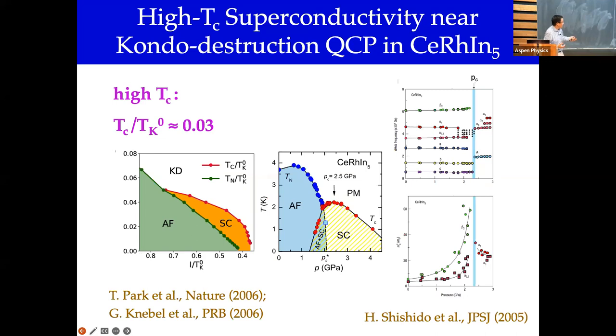So we surmise, we propose that this is a mechanism to understand this high TC in this class of materials. It is actually only 2.3 Kelvin, so it's very small in the absolute sense. But if you measure it in terms of effective Fermi energy, this would be 5%. And the theoretical calculation gets a few percent. Once again, the physical picture, the numbers are not particularly important. The physical picture is that you have competing processes: the exchange interaction between spins coupled to the conduction electrons, which was responsible for the quantum critical point to begin with, ends up cooperating with a superconductivity that's more robust than the conventional BCS pairing.